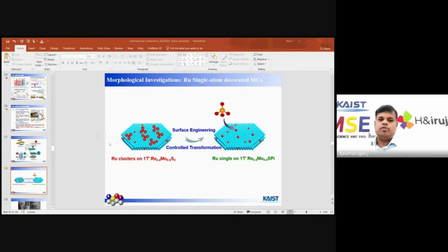Therefore, as we try to increase the single atom loading, we get a problem with cluster formation. So to avoid the clusters, we developed a new strategy of surface engineering. From the surface engineering mechanism, we go for more than 10% single atom loading. So we can load single atoms of ruthenium over rhenium molybdenum sulfide, and after phosphorization, we get the single atom over the 2D material of rhenium molybdenum sulfide networks.